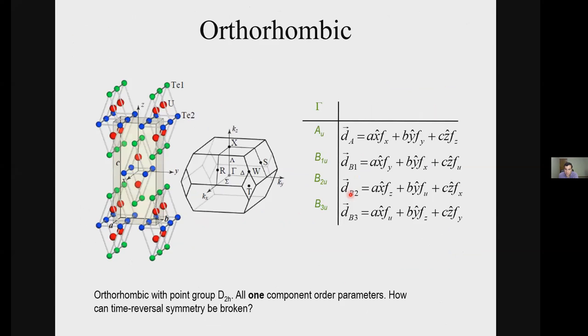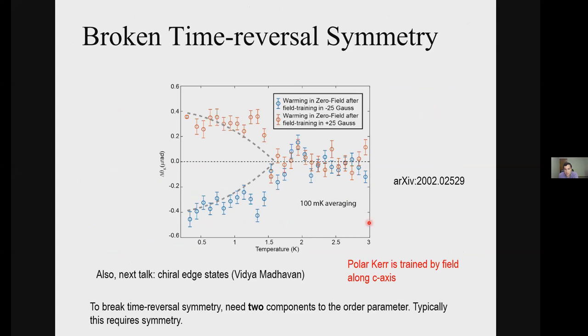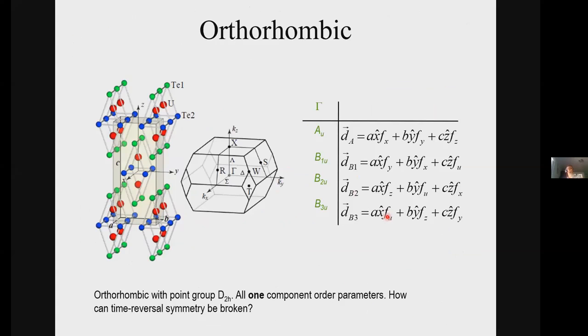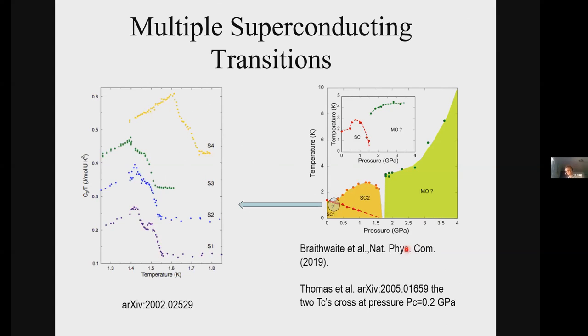I know there's a debate whether it's ferro or antiferro, but regardless, what confuses me is that if both superconducting states are triplet, which has to be the case if you want to have the Kerr effect, of course, they have to have the same parity. Why would one of them be essentially killed as you approach a magnetic phase and the other be enhanced? This would seem naively to be more consistent with a singlet and a triplet. I know this then contradicts the Kerr experiment, but I wanted to know if you have an idea about that.